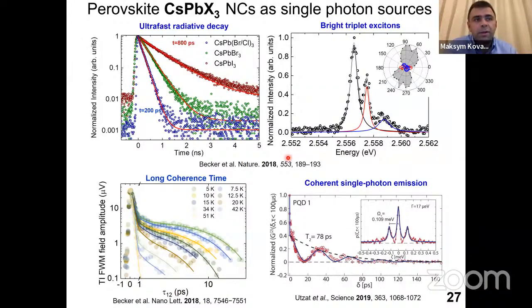And what was also extremely exciting, and this is essential for the future, is that they can retain at low temperatures their exciton coherence for a decent fraction of their radiative lifetime. And so basically they are reasonably coherent emitters at the single photon level, and this motivates building collective states where potentially these single emitters might couple into larger aggregate states with coherent emission as a collective state. And so one way to design such aggregate states would be to self-assemble quantum dots into superstructures.